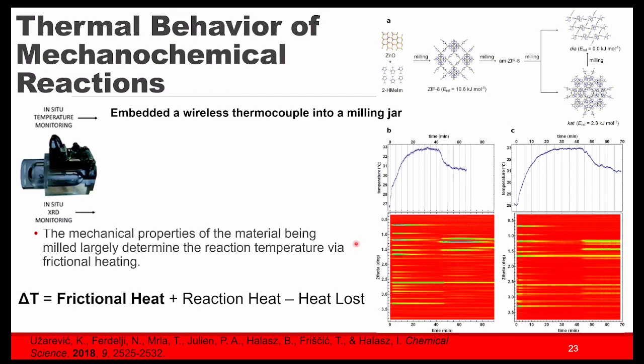In this case, the axes are flipped, so you have time going this way and 2 theta degree. And on top here, we have the temperature. We're able to read the temperature with really high resolution and quite high accuracy through basically a metal plug, which is in contact with the inside of the milling jar. What's really interesting is that you see a pretty rapid and significant increase in temperature.